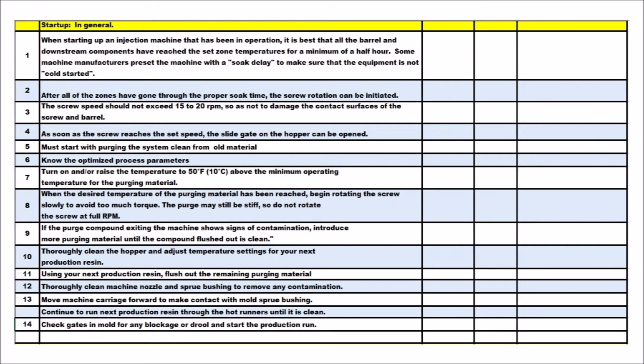Turn on and/or raise the temperature to 50 degrees Fahrenheit or 10 degrees Celsius above the minimum operating temperature for the purging material. When the desired temperature of the purging material has been reached, begin rotating the screw slowly to avoid too much torque. The purge may still be stiff, so do not rotate the screw at full RPM. If the purge compound exiting the machine shows signs of contamination, introduce more purging material until the compound flushed out is clean. Thoroughly clean the hopper and adjust temperature settings for your next production resin.